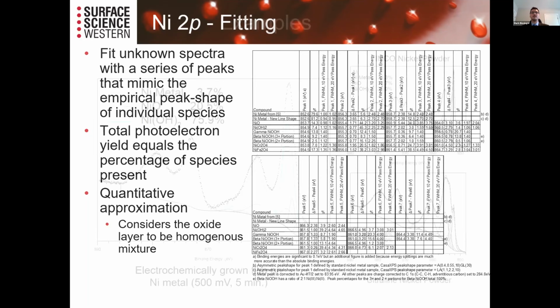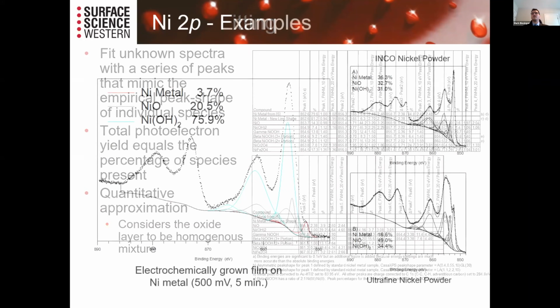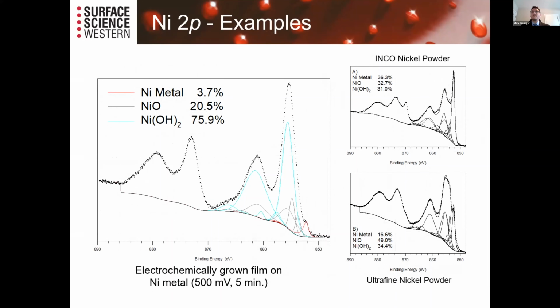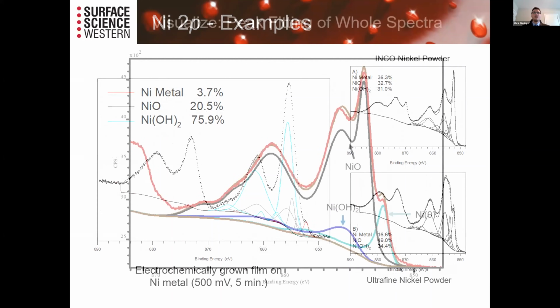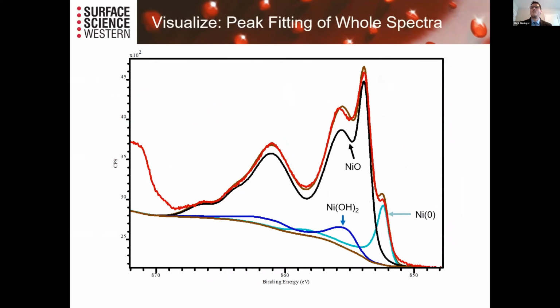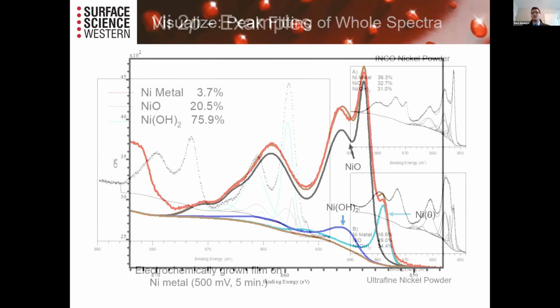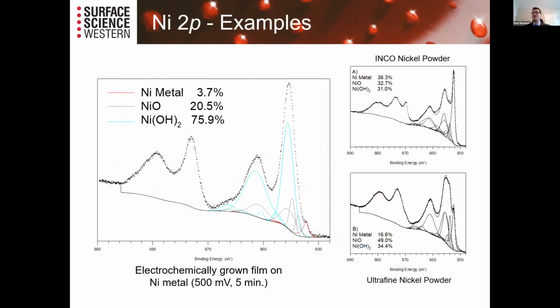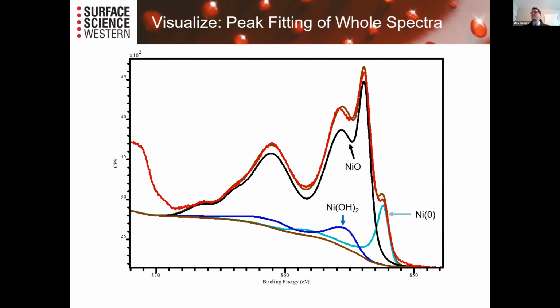You can see that these parameters work for a large number of samples. We've been using them for 10 or so years now, at least. We've had very good success with them, being able to pull out chemistries from different materials. And I should mention that even though it looks like a whole mess of peaks here, all we're doing is mimicking the overall peak shape of the standard samples. This is not a new phenomenon. People do this in infrared spectroscopy and other spectroscopies, where they take standard spectra and use them to pull out what they have in a mixture of materials.